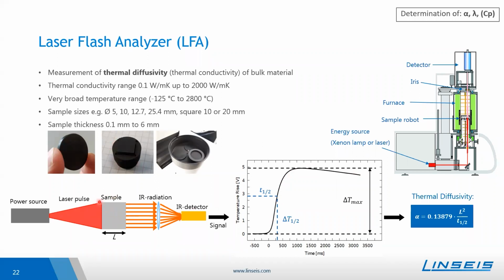The graphite coating is used as the absorption of the energy will be then maximized, especially, for example, in the case of a metal with a shiny surface. This black and matte surface helps a lot with absorption. From this curve, one can obtain then with some models the thermal diffusivity according basically to this formula, so that the sample thickness is also relevant for the analysis.